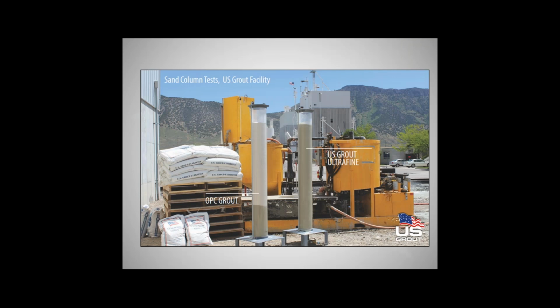Here's an example of a sand column test. This was done at our plant in Malad City, Idaho. But these are also replicated and done at the Colorado School of Mines annually at their different grout schools, as well as the one down in Phoenix, where they actually inject grout up into sands. And you'll see here where ultrafine cement was injected into this 6-foot column, and it actually went the full height of the column, whereas an ordinary Portland cement only went about 20 inches. So the driving factor in that is the particle size of that particular material.